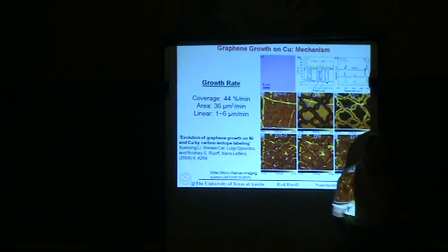And the wrinkles, remarkably, if this is a grain boundary in the copper right here, typically run by and large orthogonal, so that the graphene grains, remarkably, will span the grain boundaries in the underlying copper grains. So copper is a sort of fascinating system compared to some of the other metals. Per ab initio calculations by theoreticians, copper and the other noble metals such as silver and gold are considered to be physically interacting. There's no chemical interaction at all in terms of the bonding orbitals. In contrast, like I told you for nickel, there's significant overlap in this chemisorption. And so copper in some sense is a more forgiving system for growth. It doesn't have to necessarily be epitaxial growth and lattice match. In some sense, in the theory that's being developed for our experiments, the carbon species kind of float around on the copper and move very readily on it, and they're more likely to interact with each other than with the underlying copper.